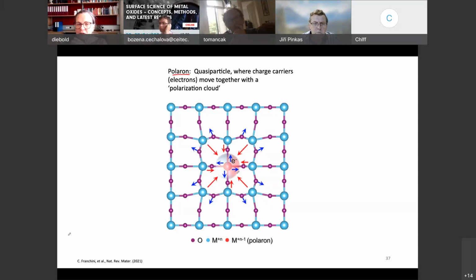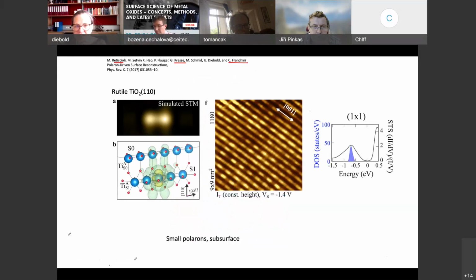well the system conducts. It matters for the optical properties, it matters for the chemical properties. So these electron-phonon interactions, or this interaction between an electron and the ionic lattice, is a very active matter of research that we have discussed in this paper. I will not go into details, but the nice thing is that with STM, with filled state STM, one can actually kind of see the effects of these polarons, the effects of these electrons that are gap states that are really important for the properties of these materials.